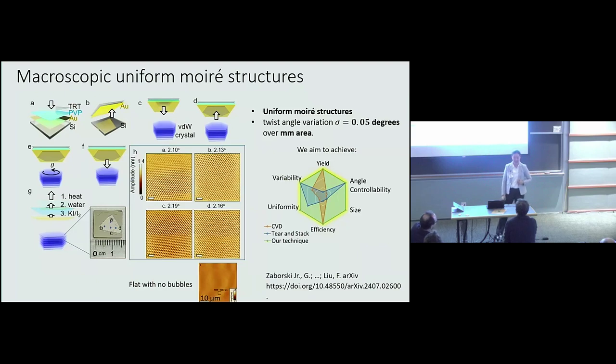So it means that the surface is really not that reactive? The surface is not that reactive. That's the nice thing for the 2D materials. There are no dangling bonds, and it is atomically flat, and all the bonds are saturated, so it's not really chemically active to bond to these species. But of course, if you leave the surface in air for a long enough time, like what other people have done in the pick-up and stack method, in that case, you would expect to see a lot of contamination.